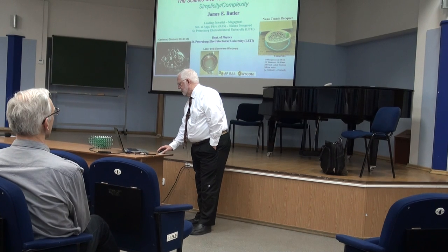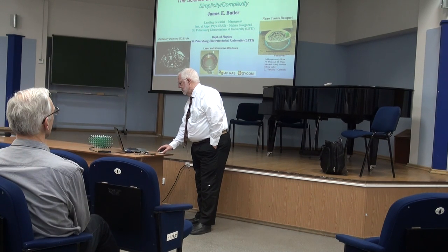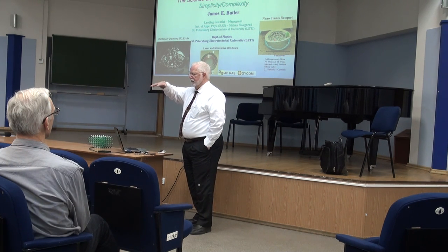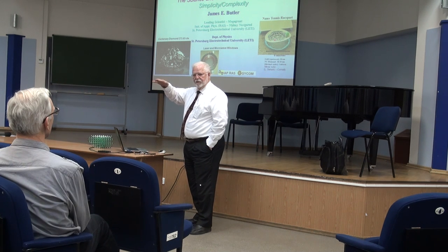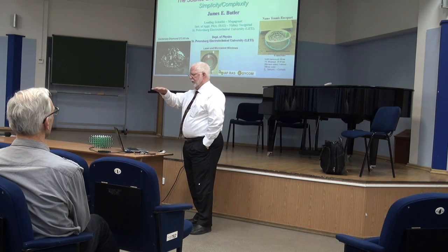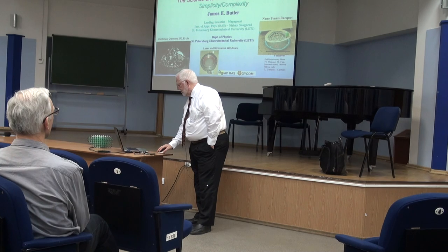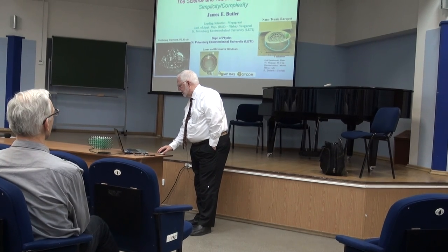was then patterned and etched to create this 6-micron diameter paddle. And we were doing this to make resonators, very high frequency, the microwave frequency resonators. And to measure these resonators, we sputtered a very thin gold layer on top. And you can see how it was masked, and you can see the gold underneath here.